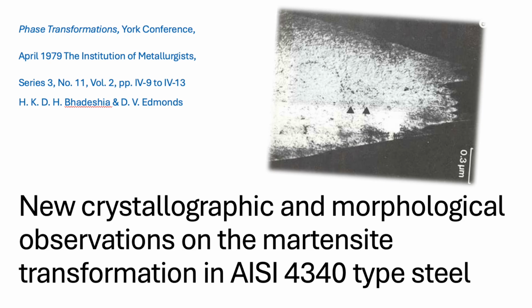That structural difference is pretty telling, but wasn't there some physical evidence, something they saw that really nailed the case for the packet being the unit? Yes, absolutely. It came from looking closely at the stuff between the laths, specifically retained austenite. Austenite that didn't transform. Leftover parent phase. Exactly. The rapid cooling traps small amounts of the original austenite structure. And the sources observed very thin films of this retained austenite sandwiched between the parallel laths that make up a packet. Okay, I see the film exists, but how does that prove cooperation?